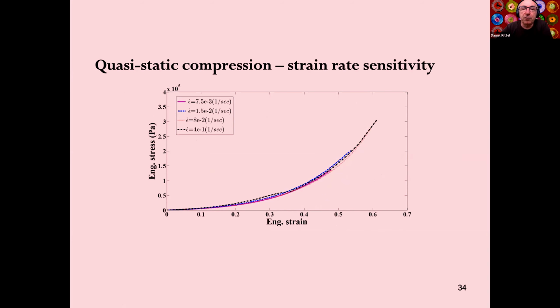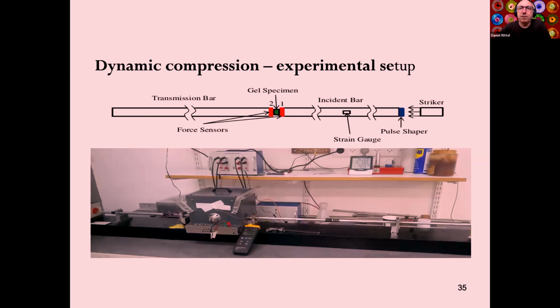Quasi-static compression, strain rate sensitivity? None. As you can see, there's no real strain rate sensitivity. Dynamic regime, well, that becomes a little more exciting here. We have to test a soft material. So using a Kolsky bar is nice, but it's not sufficient. The strain gauges are not going to react mostly on the transmitted part. So what we use is force transducers by the name of FlexiForce, piezoresistive force transducers. And we measure directly the forces on both sides of the specimen.